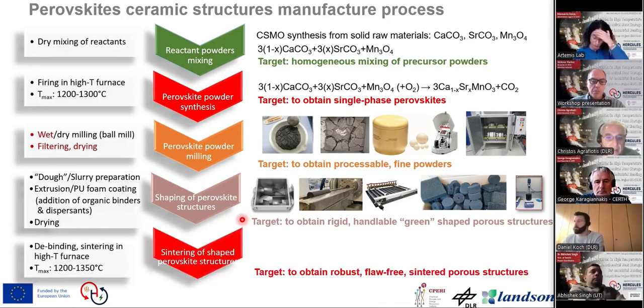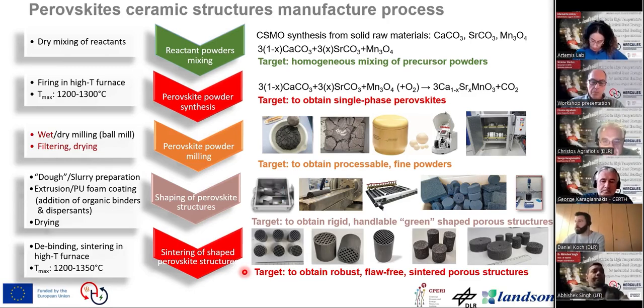Finally, the last step is to sinter this shaped structure again at high temperatures, 1200 to 1350, in order to obtain robust, flaw-free, sintered porous structures with which we can assemble our unit. If we click, we will see which kind of structure we would like to obtain, and these are manufactured in the project, as I will show later.